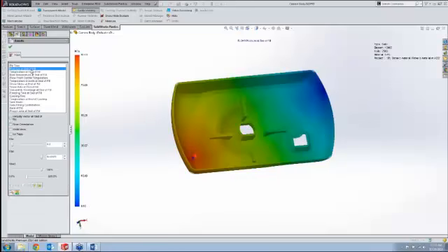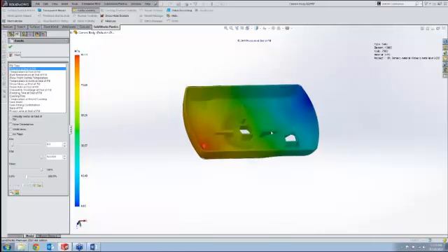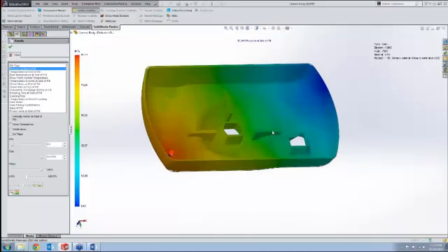You can also take a look at the pressure at the end of fill, and this is generally a direct inverse of the fill time, right? So what you see in red on the fill is generally what you're going to see as the lowest pressure inside of the plastic mold, where the last thing to fill is going to be the low pressure. The first thing to fill is going to be the higher pressure area.